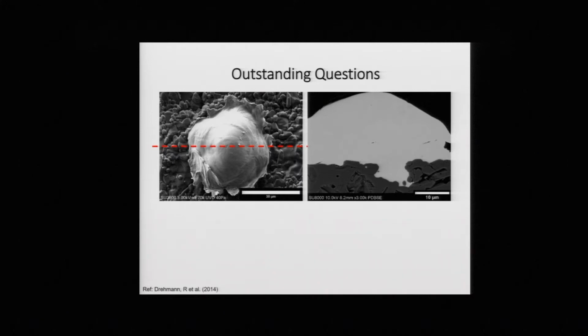And why do we get this low bond strength? To understand this, we need to go to the scanning electron microscope and analyze the cross sections of these interfaces. And what we can see is the morphology at the interface, and we can understand if there's any chemical changes or if the composition changes at that interface.